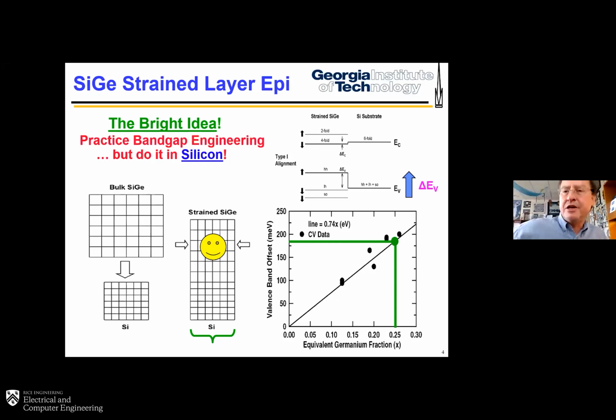If you look on the upper right, what that does from a band structure perspective is interesting. So the silicon substrate on the right, and if you remember from your silicon semiconductor physics, you've got a band degeneracy in both the conduction and valence bands in silicon. That lifts in strained silicon germanium. We have a very slight compression of the conduction band edge, but importantly, the heavy hole band lifts in the valence band by an appreciable offset. And that actually is what we're going to be using in our engineering problem. The band offsets are shown in the lower right. So we're talking modest offsets with respect to what you might see in the III-V world. At about 25% germanium, we're talking about 175 milli-electron volts of band offset, which seems like a small number. But if we, as you see, compositionally grade that over a tiny distance, then we can generate enormous quasi-fields in our system. And that's what we're going to use here, as you will see.